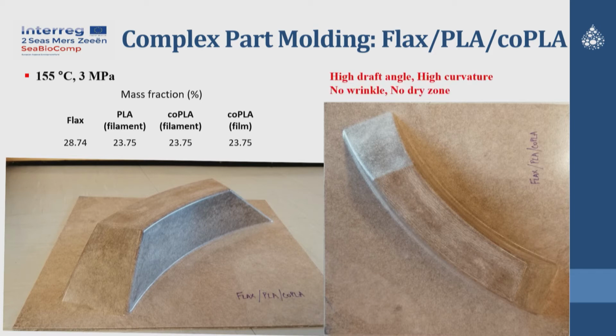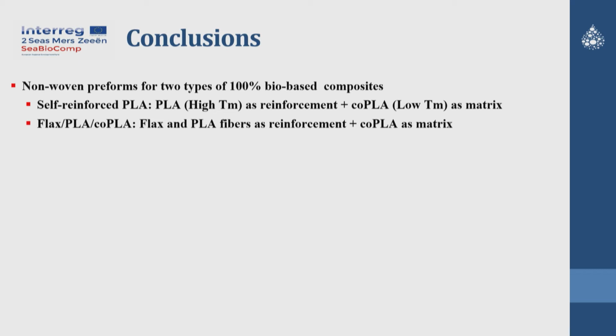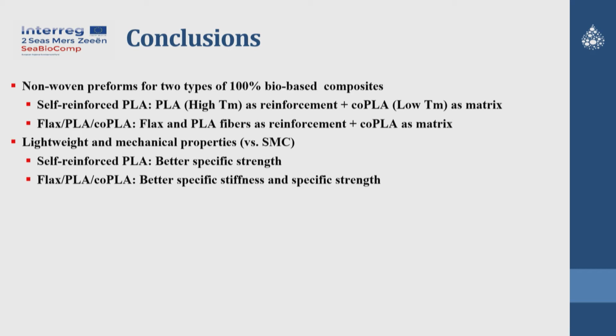So anyhow, without any kind of special treatment or pre-processing, so no wrinkle and no dry zone, we could obtain perfect manufacturing quality using this process and materials. So we can say that we developed two different kinds of 100% bio-based composite preforms compared with the conventional SMC.